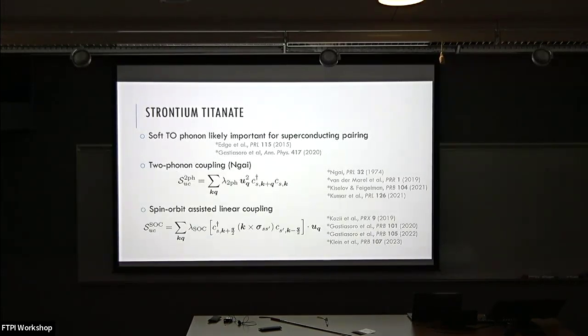And now there's 2 options that I will discuss, that were also mentioned in the previous talk. One is this two-phonon mechanism, which is basically a displacement square kind of coupling. So this involves the exchange of two phonons. And this has been suggested way back in the 70s, but then recently it's been revived. And there's been attempts to explain both the normal state and this pairing. And the second is this spin orbit assisted coupling. Now, this is quite a special thing. It's linear in the phonon amplitude, but it involves the electronic states, the k cross sigma. So this is a very strange kind of coupling, which I don't think has been directly observed. So basically now the question is, you have these two possibilities, which of them, if any, is relevant for the physics of the system? And this is one of the questions that we're trying to answer with what we're doing.